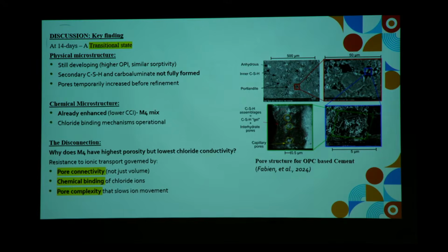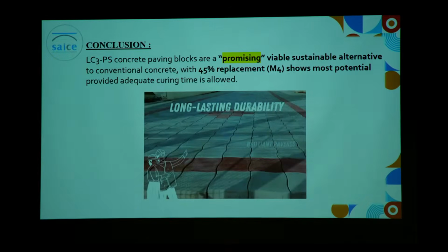So that disconnection, like I had said, with the sorptivity and OPI having poor results when we're replacing our study materials, but as soon as we get to the chloride conductivity, we're finding good results. It's showing that at that stage, as much as it is an early stage, we are finding that our chemical microstructure has already developed very much.